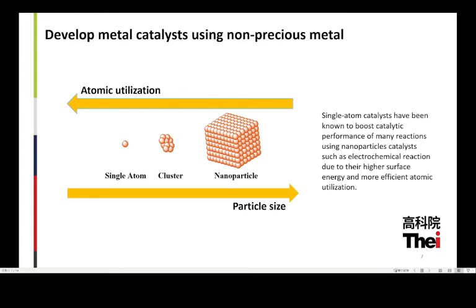To develop an optimum catalyst, we use two single-atom catalysts, which are cobalt and copper, and the single-atom catalyst has been known to boost catalyst performance of many reactions using nanoparticle catalysts, such as electrochemical reactions, due to their higher surface energy and more efficient atomic utilization. Like the graph shows, the particle size decreases as the surface area increases, and this brings these benefits.